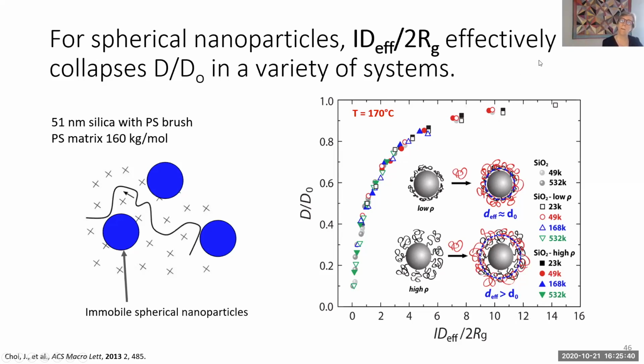the diffusion coefficient. And this is one of the reasons why we did those monolayer molecular dynamics simulations, to really convince ourselves that it's a princess and the pea, like the center of mass polymer diffusion, even if it's very far away from those nanoparticles, is impacted. And that is hard to understand why. It's hard to imagine that that chain that's so far away, that the entropy of that chain and its chain conformation could be so distorted that it would still change the diffusion coefficient. So there you have that.